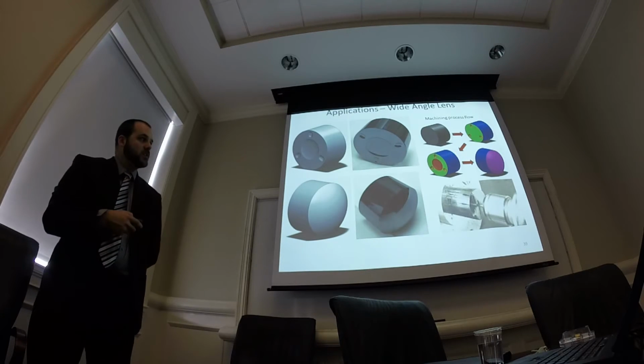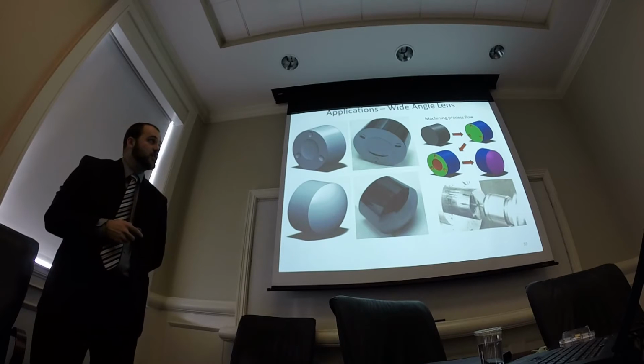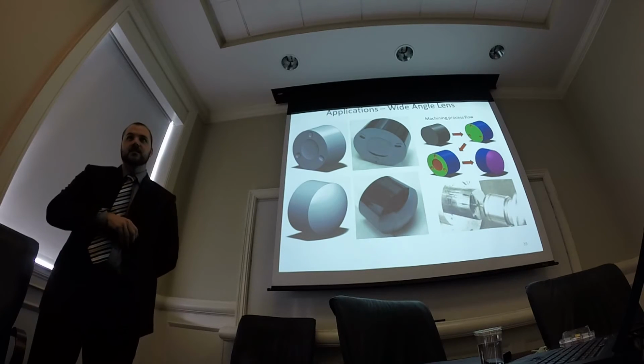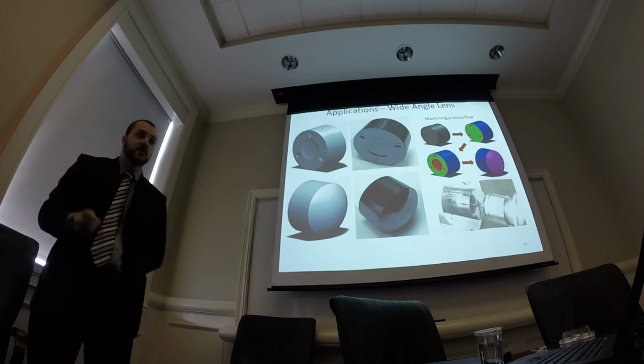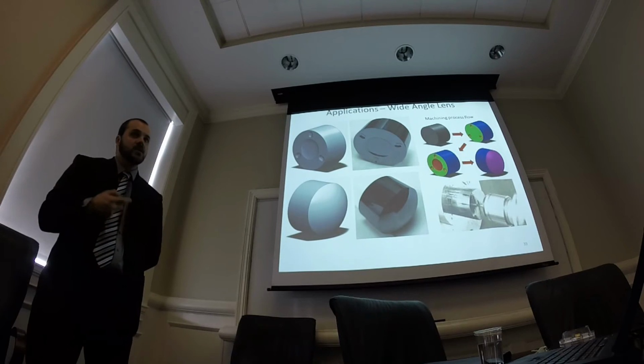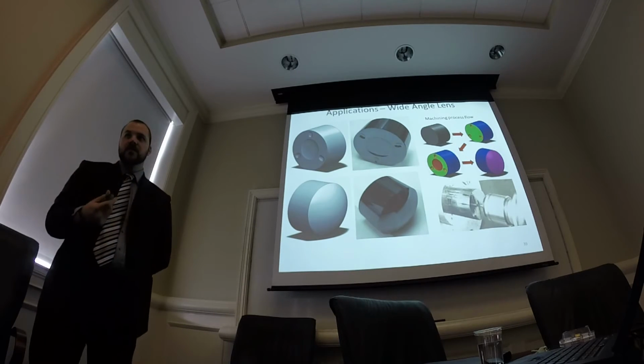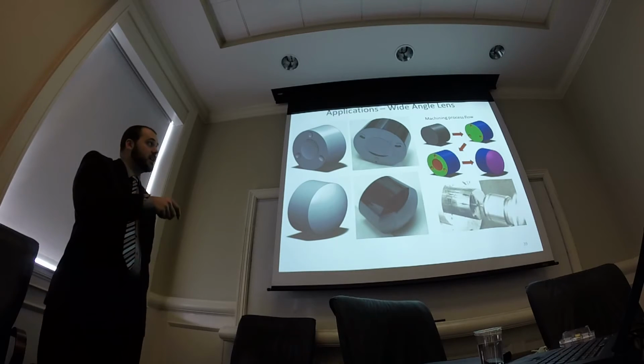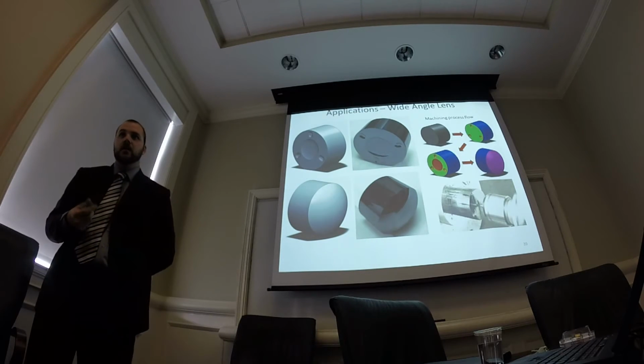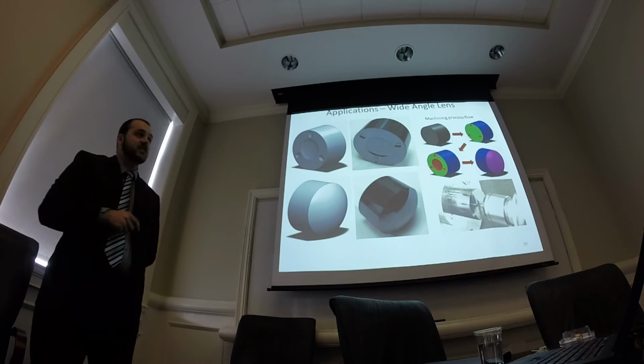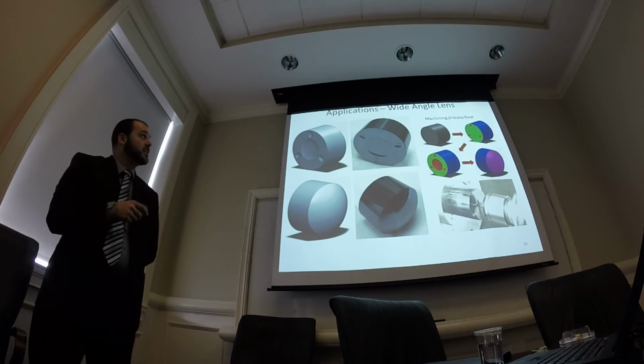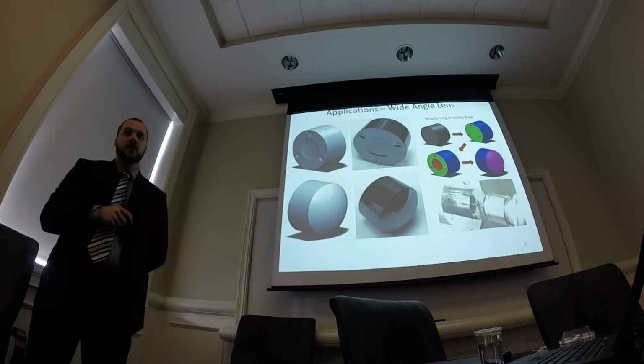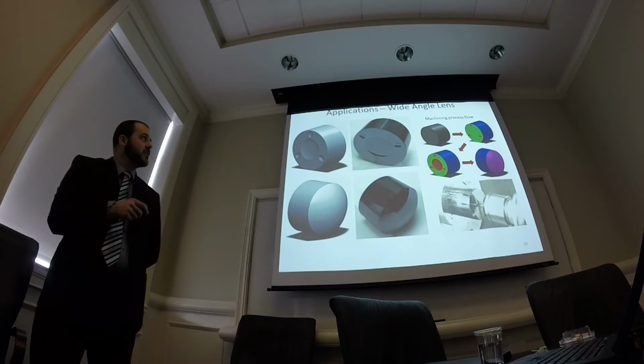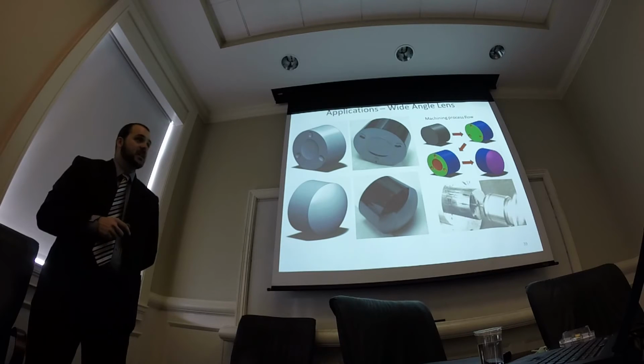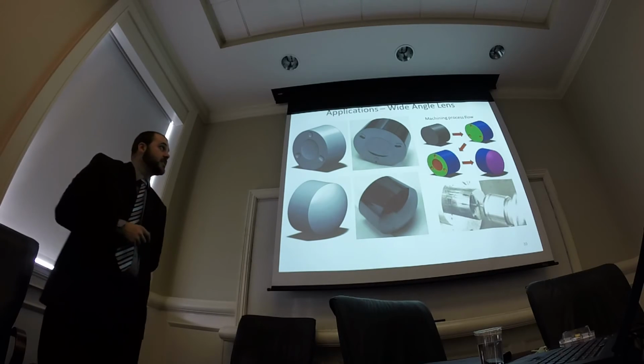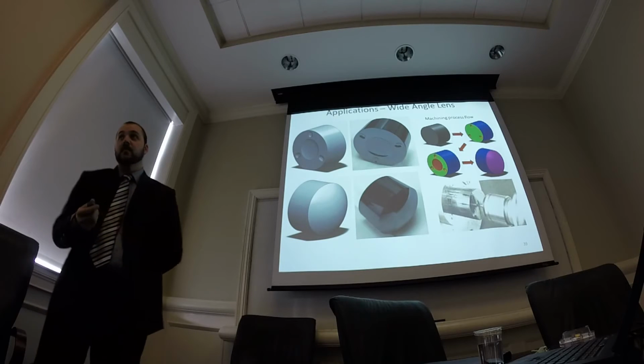So we used the technique we've been talking about. Our technique can create a relatively arbitrary surface. This doesn't show that capability, so we wanted to show everybody that with this technique you can do something. You can make a rotationally symmetric lens that you could do by turning, and we're going to add a feature that you can't do by turning. So we've got, I think these are 45-degree V grooves, 35 or 45-degree V grooves. Getting a turning tool down in there to make those would be pretty difficult, not impossible, but difficult.